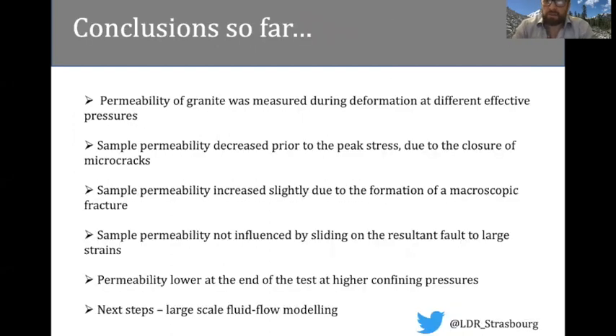So to present the conclusions so far, what we've done is we've deformed samples of granite in a triaxial press whilst measuring their permeability at different effective pressures. What we've seen from the experiments is that the permeability of the sample decreases prior to the peak stress, and this is due to the closure of pre-existing microcracks. We've also seen that upon the formation of a macroscopic shear fracture in the sample, the sample permeability increases slightly.